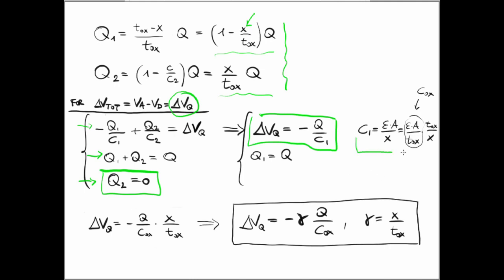And if we now remember that C1 can be written in this way, then we can quickly end up with this general result that is exactly the one that we had anticipated previously in our slide. So the presence of a charge in my device means that in order to achieve flatband, and remember that here flatband is represented by imposing this condition, that there is no charge induced within the semiconductor, the voltage we need to apply is given by this formula here.